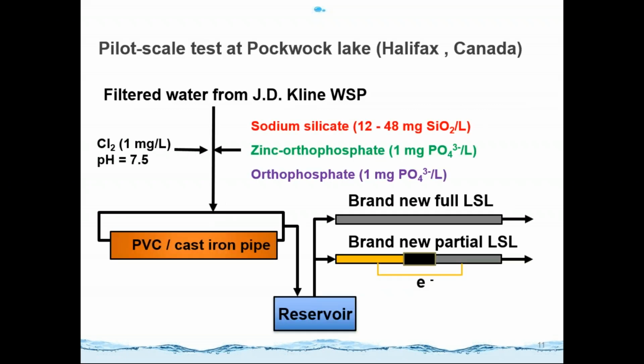So this slide shows the setup at the Pockwock Lake, Halifax, Canada. We feed the filtered water from the J.D. Kline water supply plant. Then we dose the chlorine and three different corrosion inhibitors: sodium silicate, zinc orthophosphate, and orthophosphate. Then we adjust the pH to 7.5.